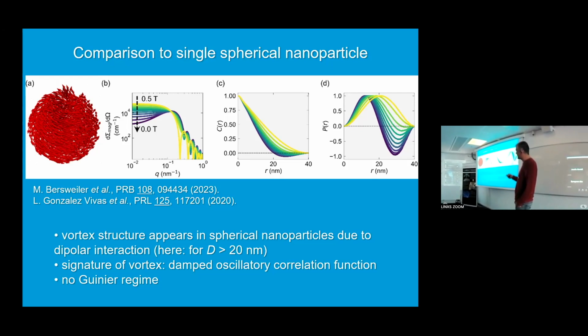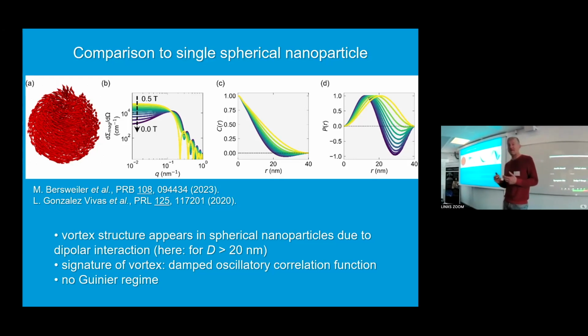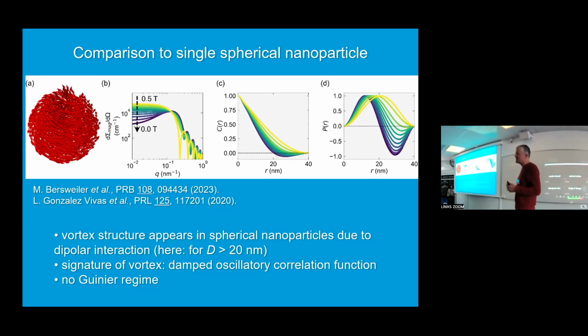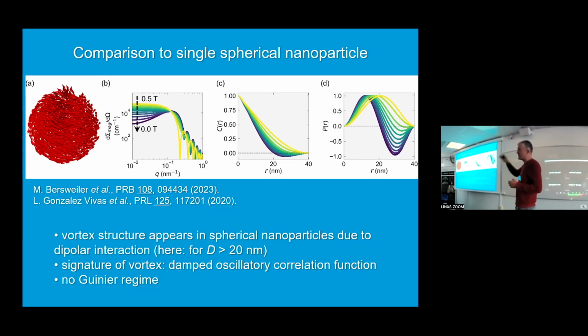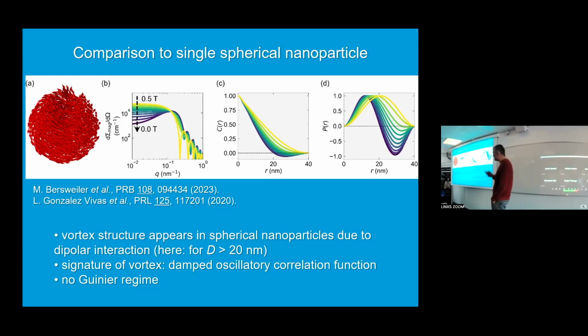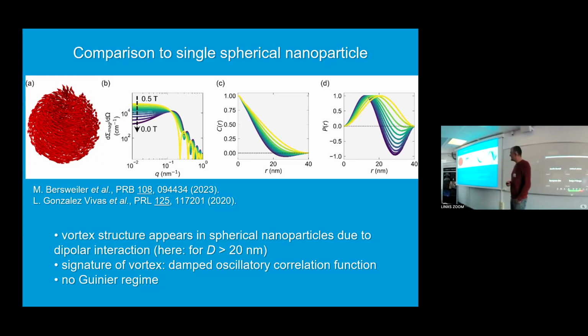This is of course one single snapshot of one particular vortex, but in the simulation this data is for randomly averaged particles. We have calculated over the whole hysteresis loop, starting from saturation going to negative saturation. We have calculated the random average for typically a few hundred different easy axis orientations of the particles, and generating such data takes of the order of 1 or 2 days.